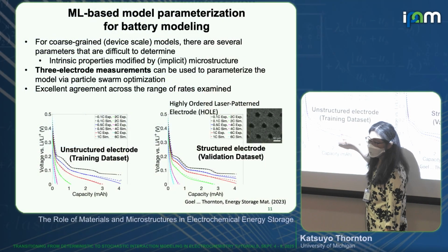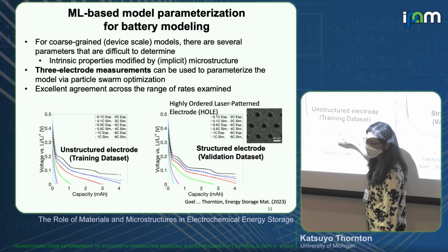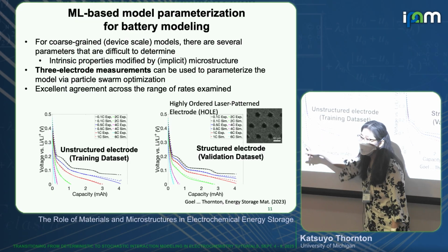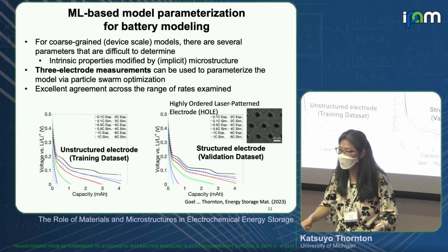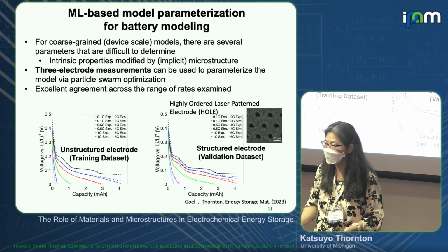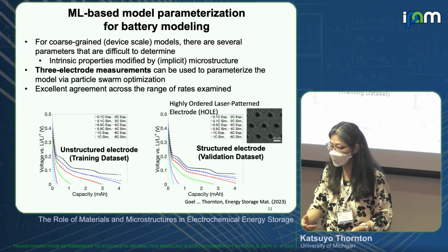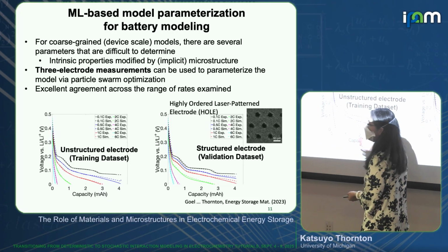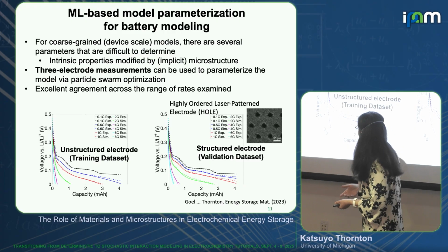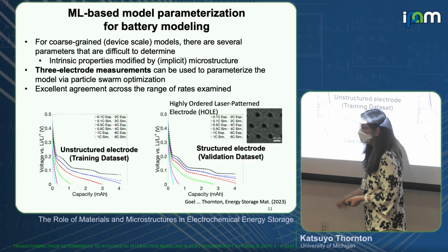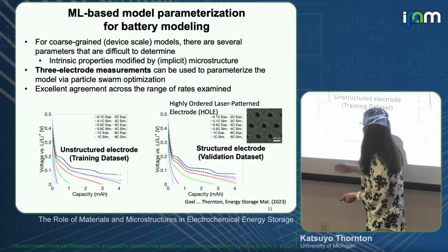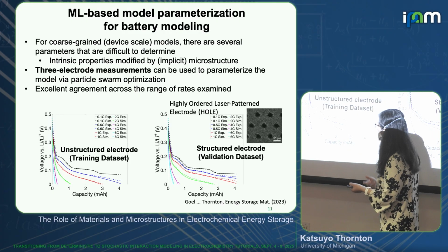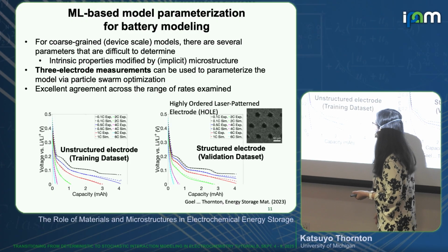And so this is mostly thermodynamics, parameterizing thermodynamics. And then this change going from here to here is due to kinetics, right? You're trying to drive the system faster and faster. You're trying to charge it faster and faster. And then there's inefficiency, and you have to overcome the concentration polarization, so you have to put more voltage towards the charging.